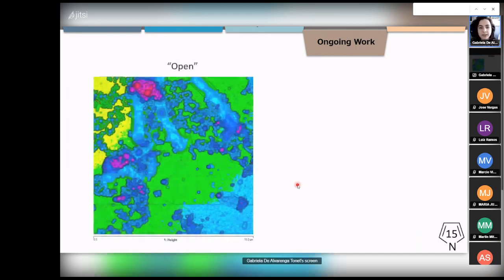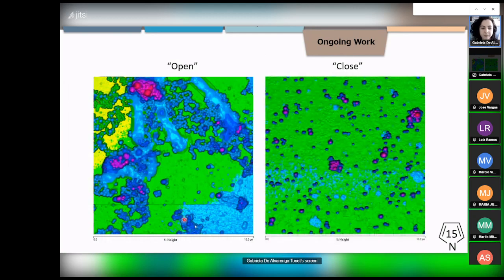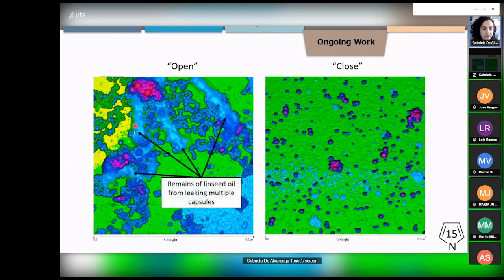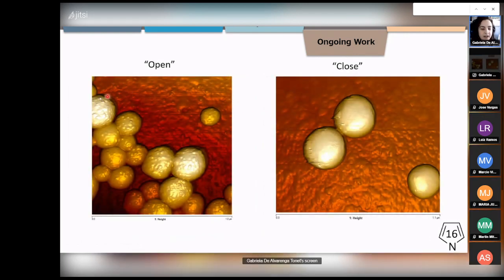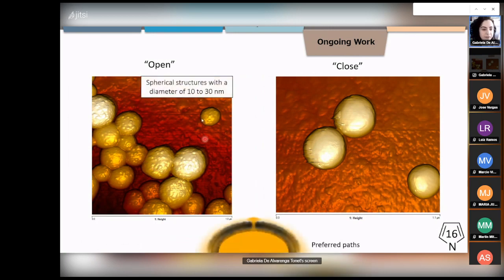Then we also submitted these capsules to AFM, and we could see remains of linseed oil leaking from the capsules in comparison with the closed solution, where nothing happens. Most importantly, the AFM gave us an idea of how this oil is leaking. We see the formation of spherical structures on top of the capsules treated with the open solution, with a diameter of 10 to 30 nanometers, and this does not appear in any other capsule. This indicates that once the shell is expanding, we are forming preferred paths for the leakage of the linseed oil.